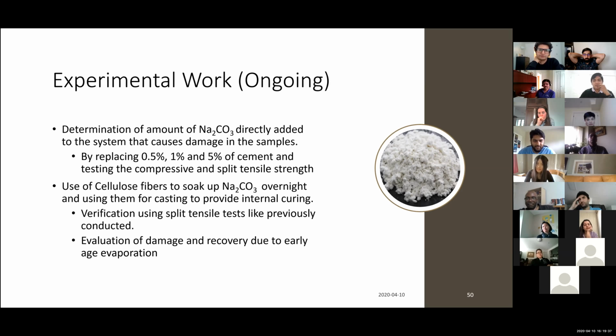Yeah, some kind of micro encapsulation. And that's what the fiber was supposed to do. Yeah, exactly. But we need to do some trials to figure out which one works. We have different types of the cellulose fiber. We figure out which one actually will work better. Because with the cellulose fiber, there's another problem. The cellulose fiber doesn't like alkaline environment. So now we are using the cellulose material to soak up an alkaline solution.